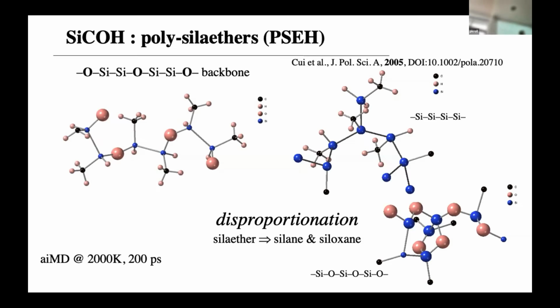Here you see a pure Si strand of the polymer, and here this is an SiO siloxane. So basically, what previously was a regular chain of SiO, SiO, and so forth, has now disintegrated. And how quickly it does this seems to depend on the amount of hydrogen attached to the silicon, because they mediate quick bond insertions, opening of Si bonds in some cases, and reorganization of your polymers.